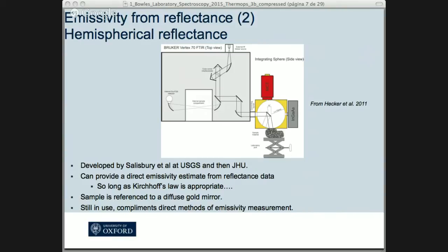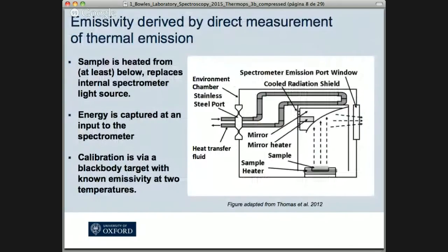The other way you can do it is to heat the sample up and measure the emission from the sample directly. Both the previous methods have used the internal hot source in the spectrometer as their thermal source that they then redirect the light around and look at reflection. The other option, which may seem like the most obvious way of doing it, but is actually quite complicated for a whole bunch of calibration reasons, is to simply heat the sample up external to the spectrometer, collect the radiation with a parabolic mirror or equivalent, then pass the light through the spectrometer, using the sample as the source, and onto the detector.